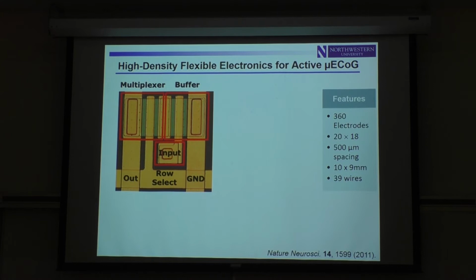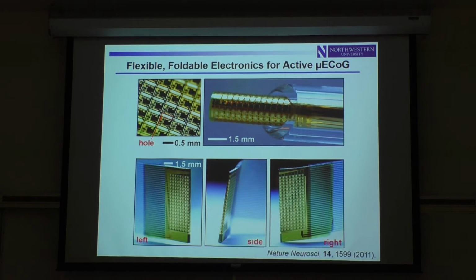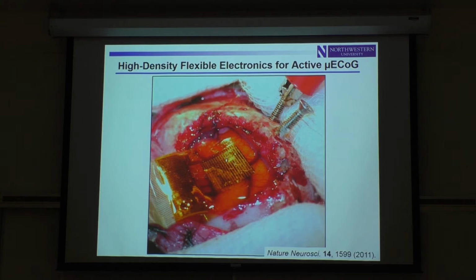So now I just need row and column address lines, and I can scale this architecture to millions of probing locations in that way. And by exploiting the kind of mechanical principles I mentioned previously, you can really render this kind of device in any kind of geometry or set of mechanics that you want. So you roll them up and you put them in a tube. You can wrap them around a soft insert and create a probing structure that allows you to even measure electrical activity in hidden interfaces such as those associated with the interhemispheric fissure or down into the sulci of the brain.